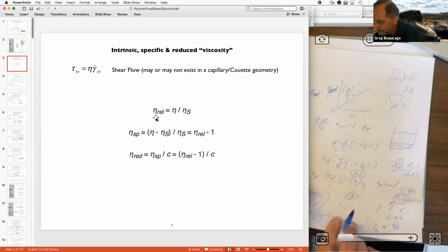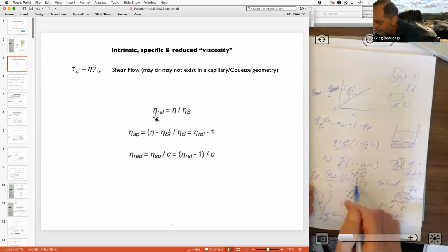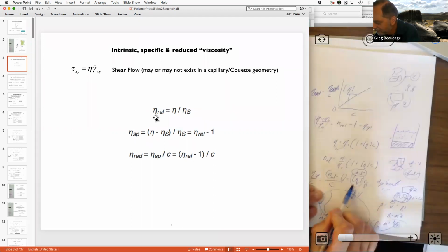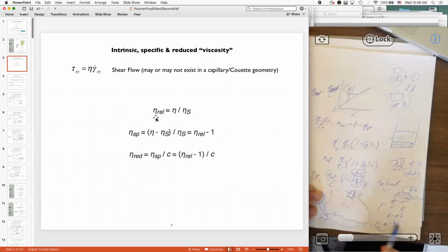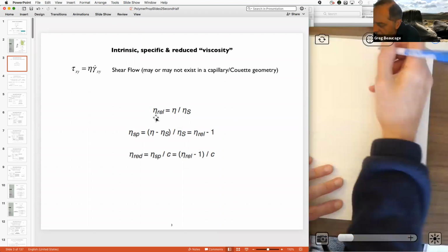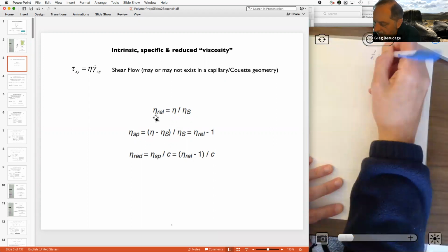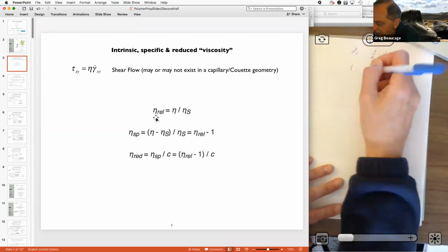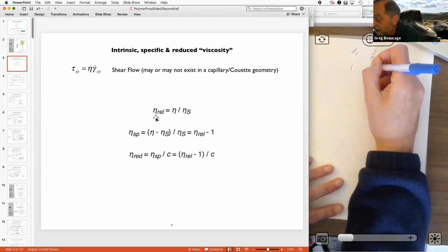Anyway, so then the intrinsic viscosity is going to have the same thing as the inverse of the density. So it's going to be molecular weight to the 3/DF minus 1. So then you can make the table. If you have DF of 1, then this thing is 2, right?